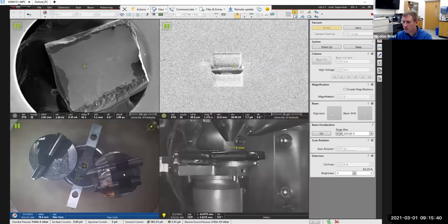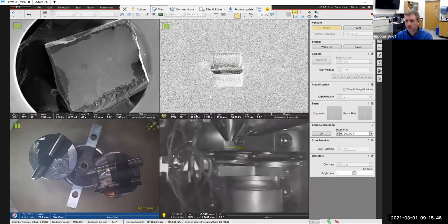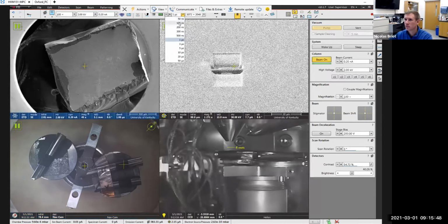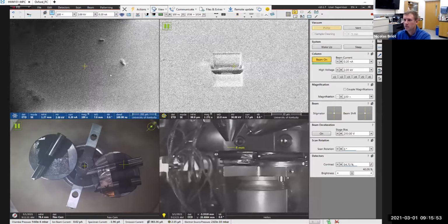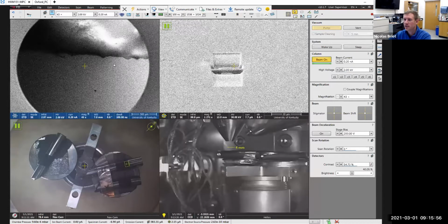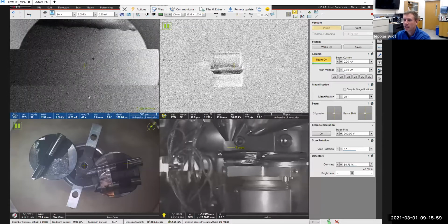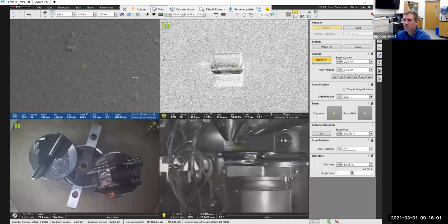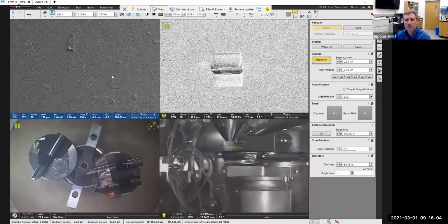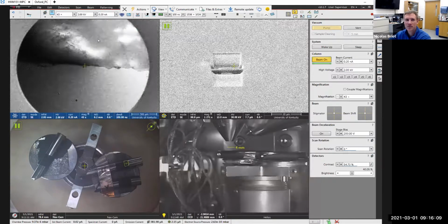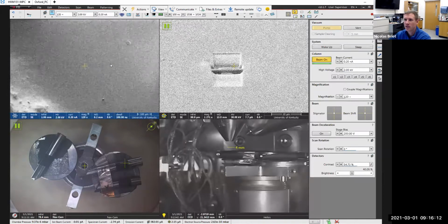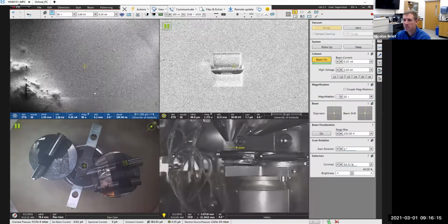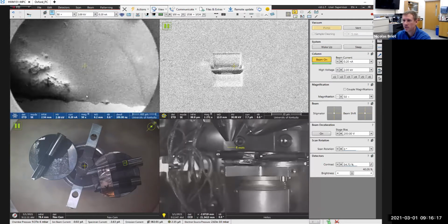So I think I'm going to go to this one first. I'm interested in this one, the clear one. Okay. You can see the edge here. If I'm in the coated region, I can go there. I don't have any problem. The system is behaving well. I can get an image without struggling. As soon as I get to the glass side, you see all those weird contrast happening, because that's uncoated. But it's not too bad with the proximity to the coated region.